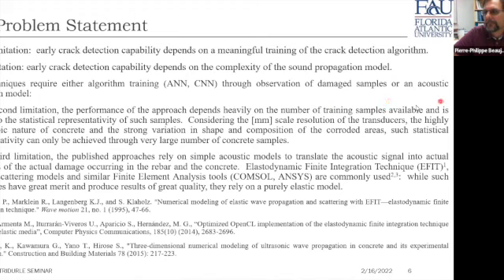Now, please bear with me just 1 second over here. Here we go. In the case of the second limitation mentioned over here, the performance of the approach depends heavily on the number of training samples available and is limited to the statistical representativity of such samples. Considering the millimeter scale resolution of the transducer, the highly anisotropic nature of concrete, and the strong variation in shape and composition of the corroded areas, such statistical representativity can only be achieved through a very large number of concrete samples. That makes it impractical because when we work, for example, on a bridge, we may only have a handful of samples we can use.